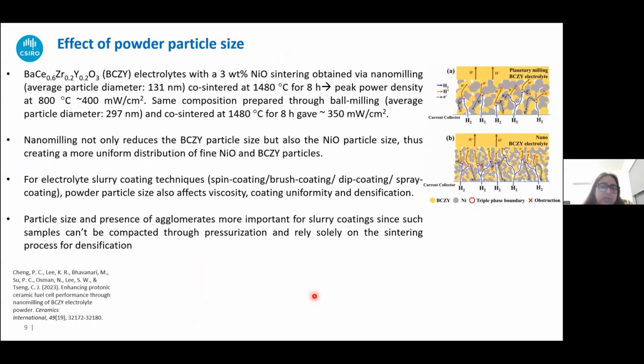Next is the effect of the powder particle size. In a recent study, it was shown that the same electrolyte material, when it was ball milled, leading to an average particle diameter of around 300 nanometer, gave an overall power density of 350 milliwatt per centimeter square, whereas when the same material was nanomilled, that is milling at a much higher rotational speed, the particle size was crushed down to 131 nanometer, and that gave 400 milliwatt per centimeter square power density.